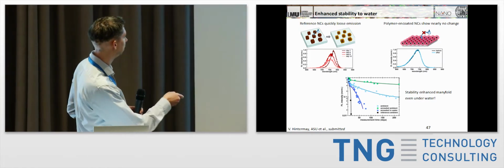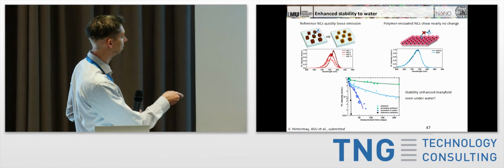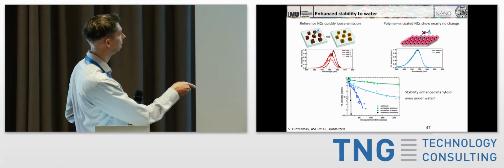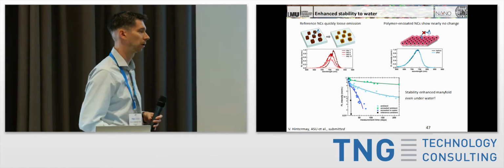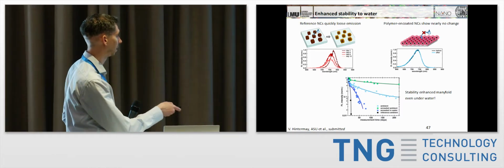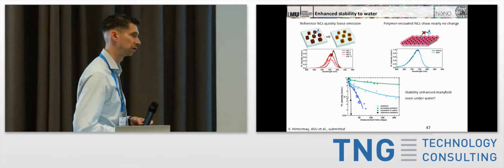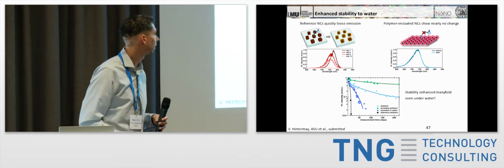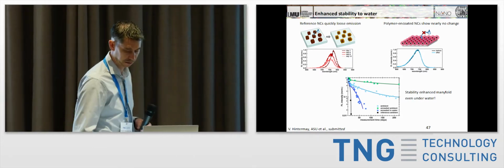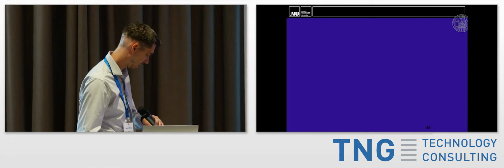And what's actually gotten us even more excited is this blue curve. You can still see a drop-off, but essentially what you have to know is that this is a film of these perovskites that's sitting in a glass of water. And it's been sitting there for 75, 80 days, and it still emits light afterwards. So obviously it's not perfect, but it's a lot more stable than any of the perovskites that we have nowadays. All right, and with that then, I'd like to sum up briefly.